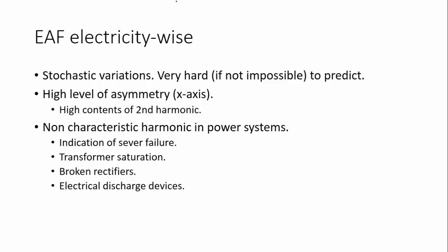When you start to bore into the scrap, the arc is very random because the scrap is in a random position. So harmonic content is high and it's very asymmetrical. When the steel is molten and you have a pool, the arc is a little more stable, and you can estimate a little better how the arc will behave. But in the beginning, it's very hard on the system because the power drawn varies a lot along with the current, and the harmonics are very unstable. Besides, an electric arc furnace is pretty much like a welding machine, but huge.